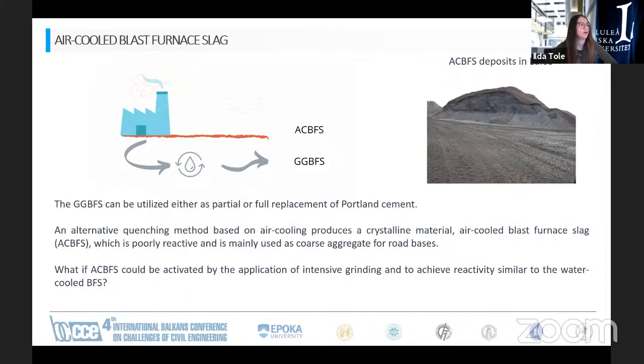Well, this material comes as a byproduct from the metallurgical process, and usually it is water quenched. Quenching with water produces the well-known ground granulated blast furnace slag, which is already utilized in laboratory and industrial scale for partial or full replacement of Portland cement. While there is actually a lot of effort to no longer utilize this kind of quenching, because the water cooling is causing a lot of pollution.